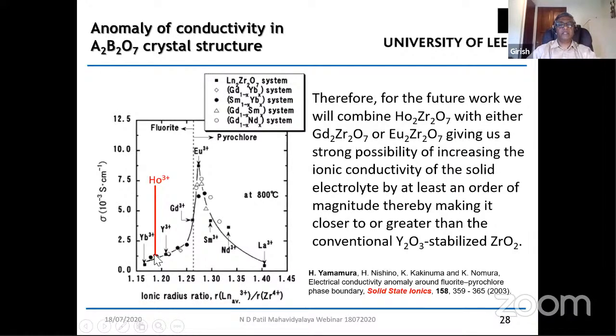So what we see here is that when you go close to the fluorite-pyrochlore phase boundary, which is a structural phase boundary shown here by the dotted line, the conductivity suddenly shows an anomaly. It suddenly increases quite rapidly around the fluorite-pyrochlore phase boundary. And then as you go away from it, it starts dropping down in the pyrochlore phase. So this is the pyrochlore domain, and this is the fluorite domain.